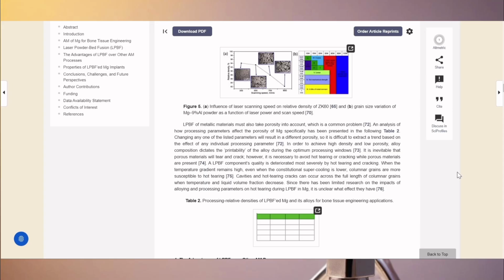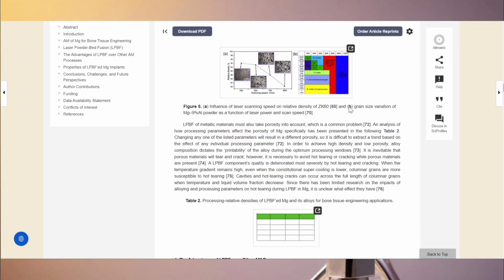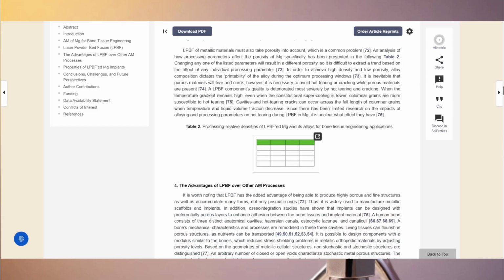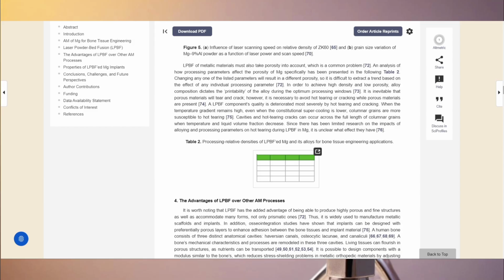Researchers tested various Mg alloys like ZK60 and WE43 under different laser powers and scanning speeds. In some cases, they nearly reached a fully dense structure. In others, excessive vaporization or incomplete melting got in the way. Figure 5 visually captures how scanning speed and laser power can shift the density or grain size of the final product. In short, the main takeaway here is that small changes in processing parameters can make a big difference in the final quality of magnesium implants. Striking just the right balance leads to more complete fusion, fewer pores, and fewer issues with the elements vaporizing. That balance, in turn, has a major impact on the mechanical performance and corrosion behavior of the finished part.